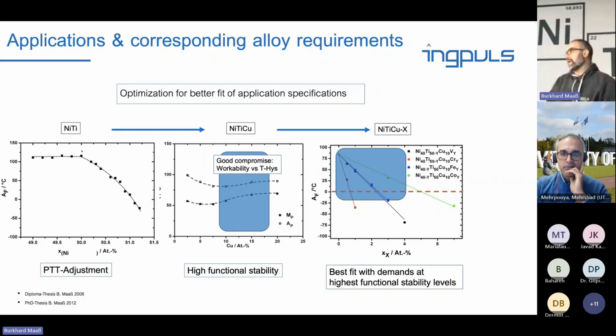Your standard medical nitinol is nickel-rich nitinol with 50.9 to 51 atom percent of nickel, with the rest of the balance being titanium. Then as you produce your alloys, you might have some precipitations. The temperatures might be prone to change again. If you do some heat treatments during your processing route, the temperatures can go up a little bit. So that's a non-stoichiometric system where you can control your phase transformation temperatures, but it's not really that simple.